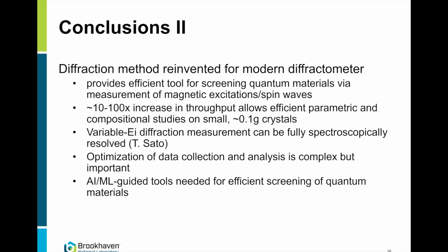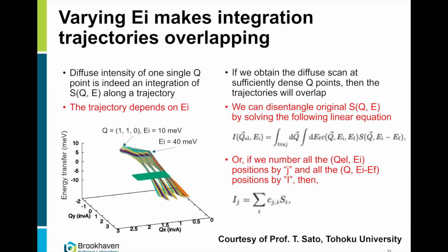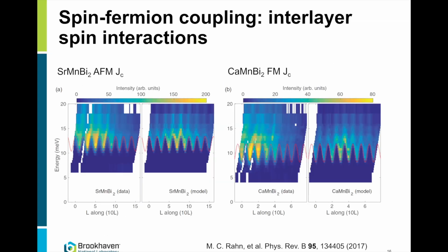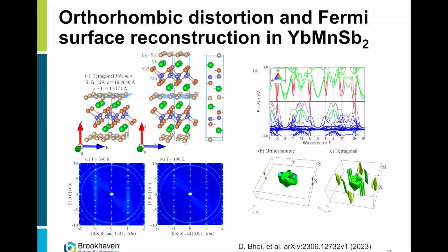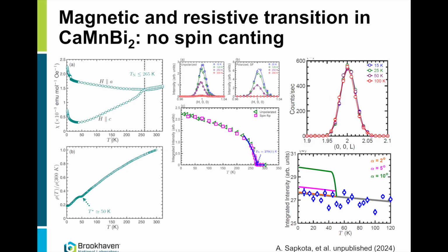First is that you mentioned that the Peierls distortion was a concern in the antimony compound. Yeah. Right. But what about the bismuth, the ytterbium antimony and the calcium bismuth? Okay, so the ytterbium manganese bismuth does not have this distortion. Ytterbium manganese bismuth does not show this distortion. So calcium manganese bismuth, as I have shown, only has this distortion appearing at 60 Kelvin. Above or below? Below. So it is a low temperature phase.